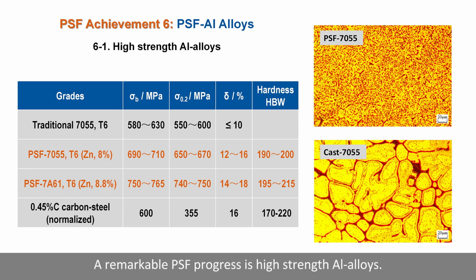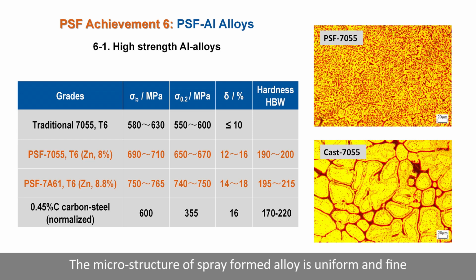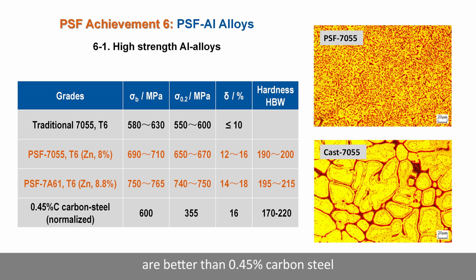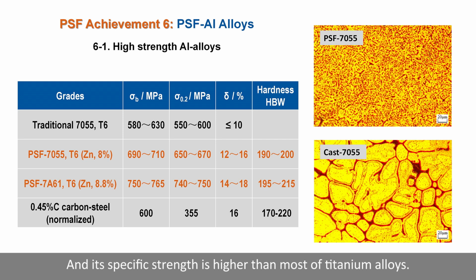A remarkable PSF progress is high-strength alloys. The microstructure of spray-formed alloy is uniform and fine, obviously better than that of cast. Mechanical properties of PSF 7A61, as an example, are better than 0.45% carbon steel, whereas its specific weight is 1/3 of steel. And its specific strength is higher than most titanium alloys.